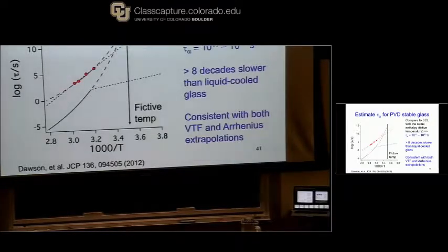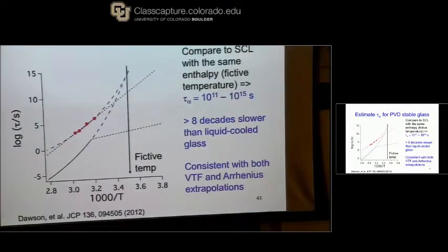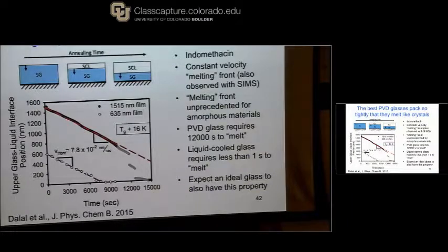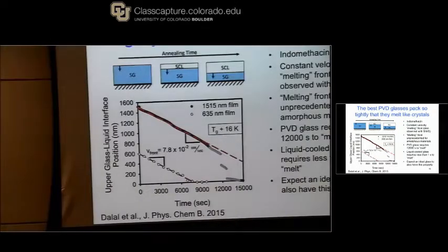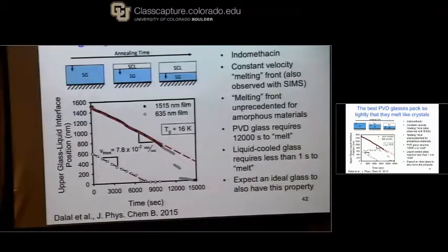Okay, so now this next story is a bit of a little sidelight, but it's such an interesting one that I can't resist. These materials have extremely high kinetic stability. And in spite of the fact that they're amorphous, and we can discuss the evidence for that more later, if you have a thin film of these materials, they melt like a crystal. Okay? That is, they start to become a supercooled liquid at the free surface, and there's a front that propagates through this material at constant velocity. Okay? Just to emphasize, this is unprecedented for amorphous materials.